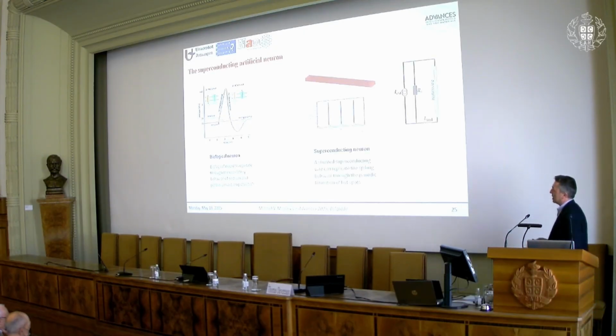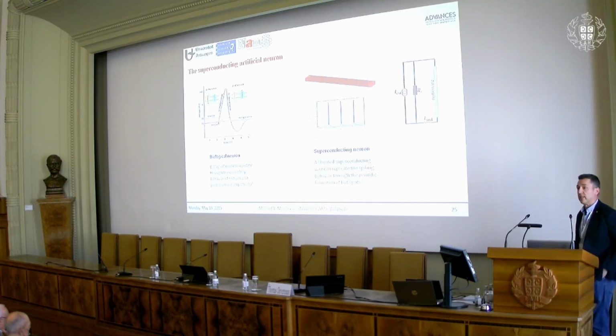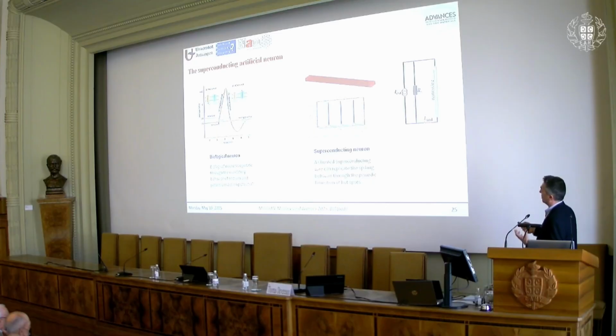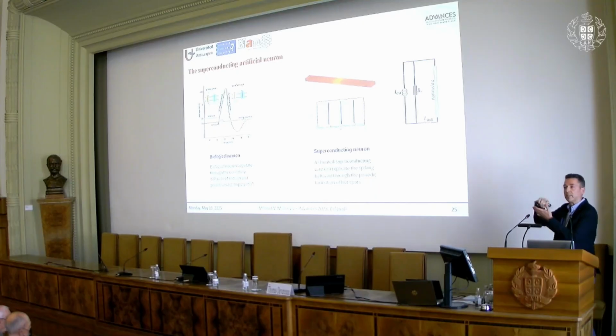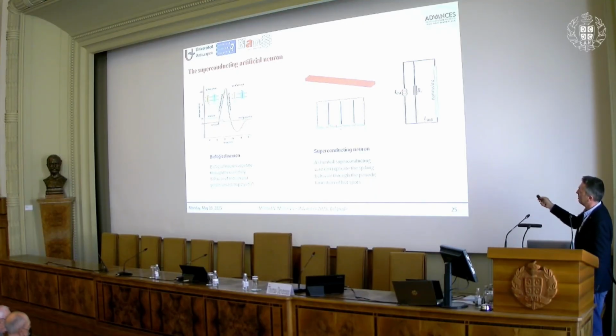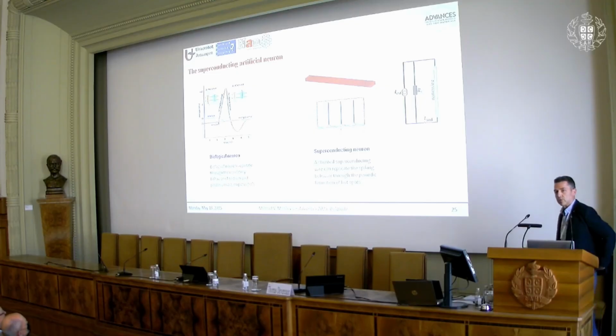What we are proposing now is to look at the resistive state of a superconducting stripe. So this is my superconducting stripe, and if we apply current and as a function of time now measure the response, we will get a hotspot for sufficiently large current that I'm in the resistive state. And if I then shunt this nanowire, then I will get reduction, and then again the rise of the peak and reduction, and so on and so forth.